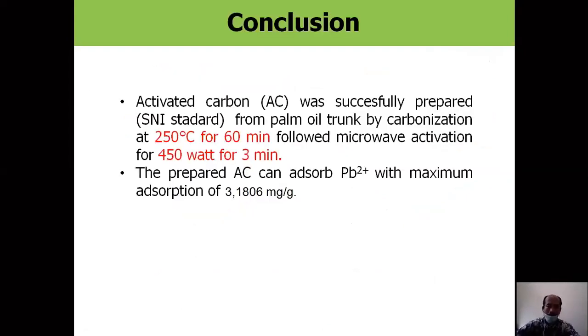And we come to the conclusion, activated carbon was successfully prepared based on SNI standard from palm oil trunk by carbonization at 250 degrees Celsius for 60 minutes, followed by microwave activation for 450 watts for 3 minutes only. Okay, we have already tested this activated carbon by lead ion adsorption, and we got this maximum adsorption of 3.18 milligram per gram. But the conclusion is not here.